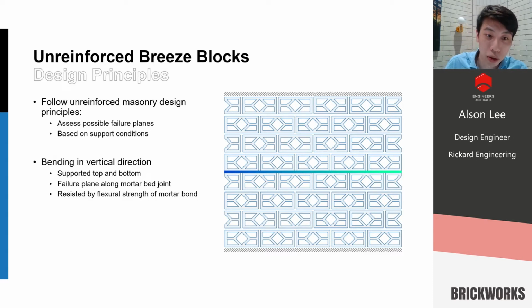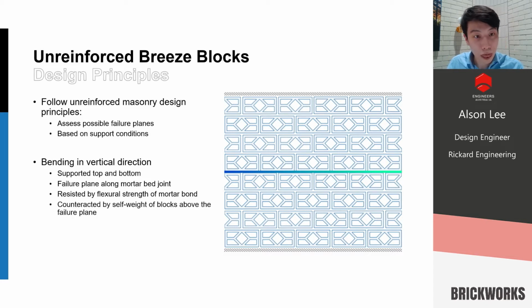This is resisted by the flexural strength of the mortar. As I've just said, the weakness is in the mortar, because mortar is not very great in tension. The flexural strength of mortar, which has been tested, as shown by my colleague Thomas previously, is quite low in most circumstances. This is counteracted by the self-weight of the blocks above, creating friction and counteracting this tension force. We have elected to include this parameter inside our block design, whereas usually it's ignored for conservative design. This will add an additional few percent of capacity, because the capacities were not great to start off with.